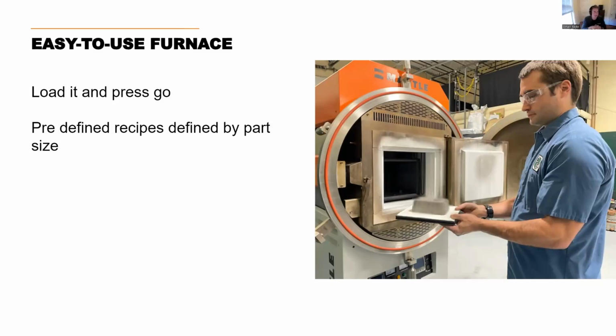What's actually happening in the sintering step is the furnace is going to get just below the melting temperature of the material. It's going to remove that binder that's left in the part. Your part's going to shrink a little bit, and the metal powder is actually going to have high enough energy, allowing it to sinter and densify together, closing up all the porosity inside your part.